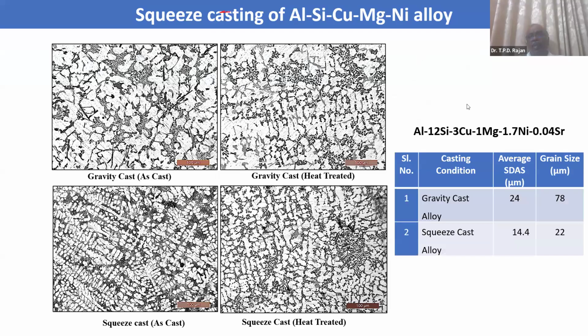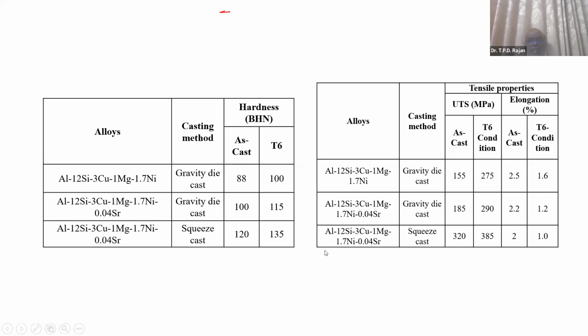Again, this is squeeze casting of the aluminum, silicon, copper, magnesium alloy, and here also we can see the application of pressure. This is a gravity cast and this is squeeze cast. Much finer microstructure cast components are formed. The grain size here is almost 78 micrometer and here it is almost 22. Looking at the secondary dendritic arm spacing, this is the primary dendritic structure and these are the secondary arms. The spacing between these structures here is 24, and it is reduced to 14.4 in the squeeze cast structures.